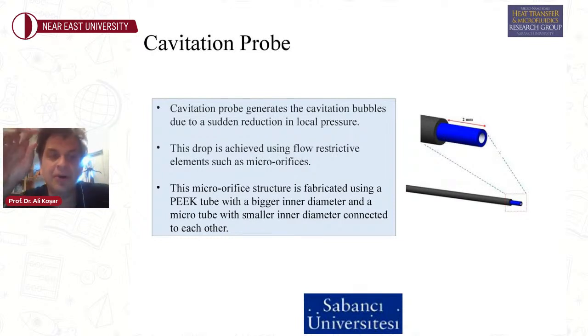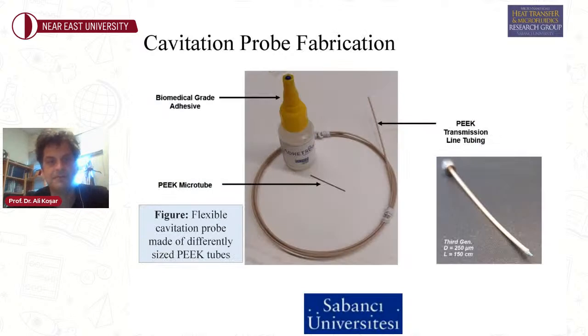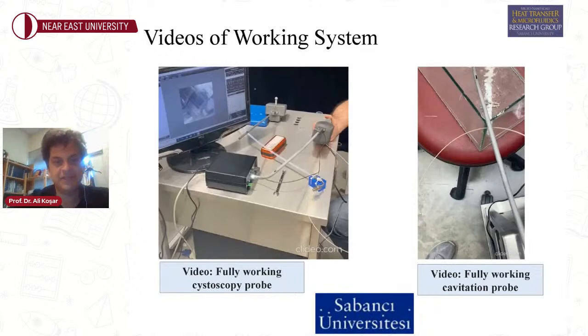It's metallic, but we also integrate an orifice made of PEEK tube, and it's rather short, a few millimeters, and its inner diameter is around 250 micrometers, so that we can generate cavitating flows, cavitation bubbles, out of this probe. And we can, of course, integrate this with the use of PEEK tube, and then we can use it first and see whether it's functioning without any difficulty. So here, as you can see, we can really manipulate the probe.